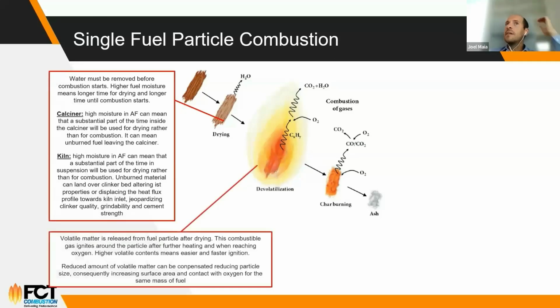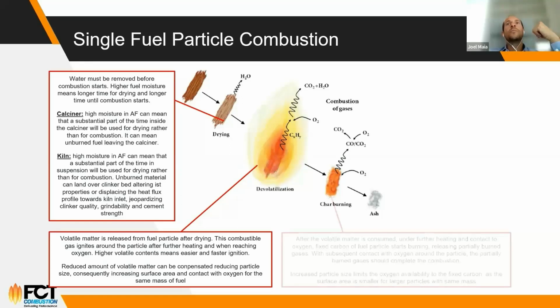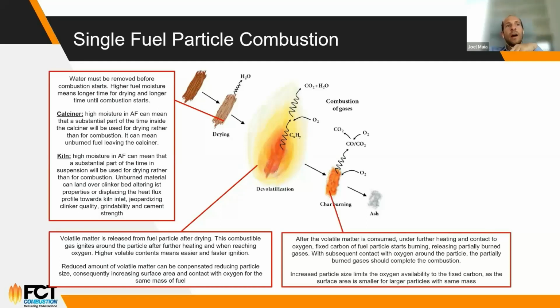After the drying is completed, the particle starts to release the volatiles, which are the easier parts to burn. In the case of some fuels, they have a lot of volatiles. For example, RDF is 65, 70, 75% volatiles. In other types of fuel, you have less volatiles. But this is a common stage of the combustion. After all your volatiles are consumed, you start burning the char, so the fixed carbon that is remaining in your fuel, and then at the end you have the ashes, right? In a case of a cement process, it will be incorporated into the clinker, mostly into the clinker.